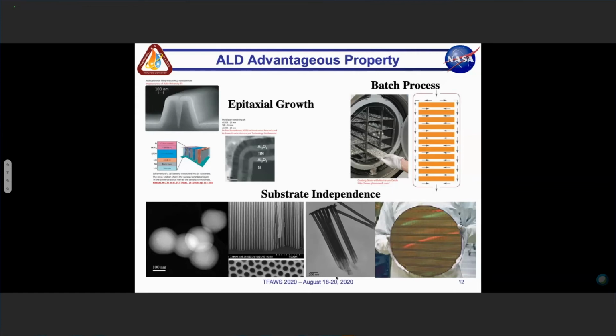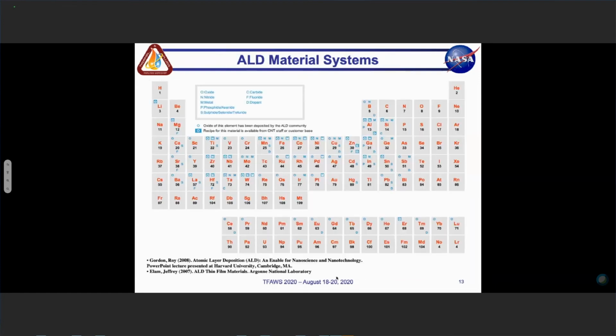Okay. All right, so talking about the epitaxial growth, what we see here is that through ALD, we can actually create these multi-layers of material with precise thickness. So you have a silicon wafer, then you're going alumina, titanium nitride, alumina, so you can create these sandwich wafers. You can do batch processes. This is an example of silver jewelry which is being covered with alumina in order to prevent oxidation. That's a protective layer that's being created. And on the bottom left, you can see some nanoparticles which have been coated with some sort of material.